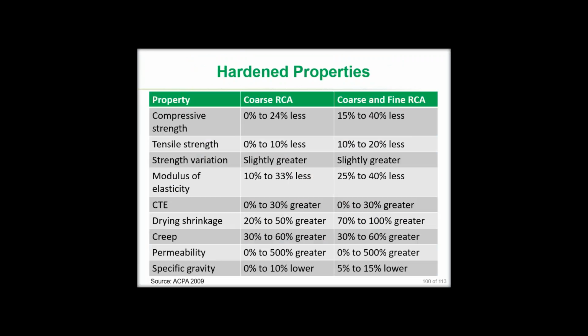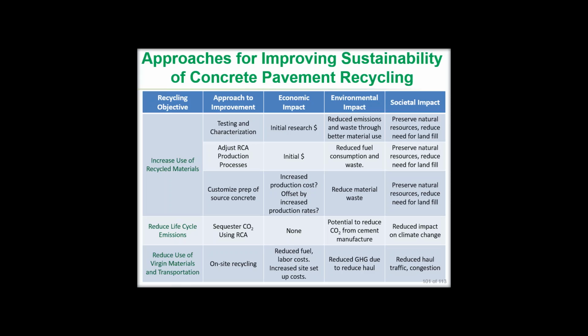properties of the hardened concrete when you're using it back into a mix. You can see those summarized here. We can make adjustments in general to minimize these impacts, with the exception of things like drying shrinkage, and you're typically going to see a little higher number on the drying shrinkage side, and we're typically going to see a little lower specific gravity, and our permeability tends to be a little higher. So those things need to be considered in other aspects of the concrete pavement design.